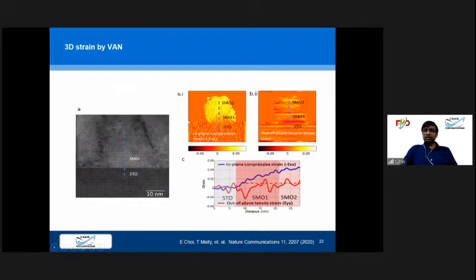We also did strain mapping in high resolution TEM. TEM also shows us that as we grow the film, in the column only, we get a very high amount of strain at the higher thickness. So this is another mapping. The yellow part is the signature of the highly strained film. We don't get any strain in the matrix or near the substrate, but you can get a high strain at the thicker film. This is a little noisy, but as you can see, the strain amount is increasing.